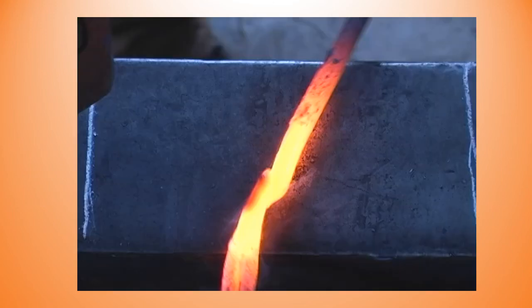This photo is showing you two pieces that have had the initial weld stuck, and then when you went to turn it you can see some loss of color here. I want you to see this because the outer pieces from the area that's lost the color since it was on the anvil are still at a nice welding heat, and this is quickly going to turn into that same welding heat as the heat goes into the cold area and you can continue to weld.